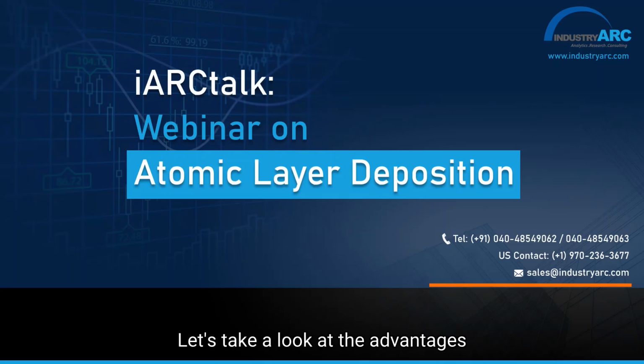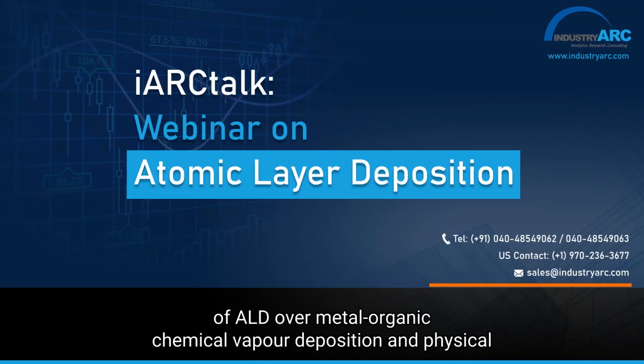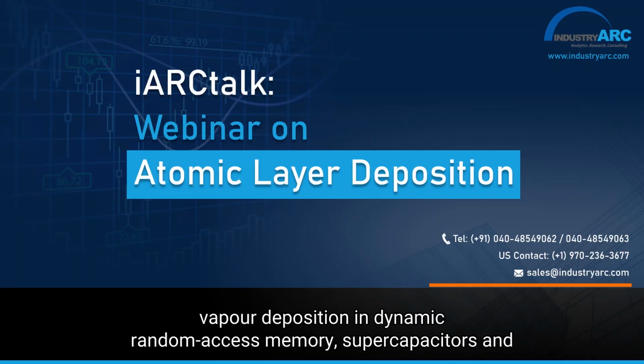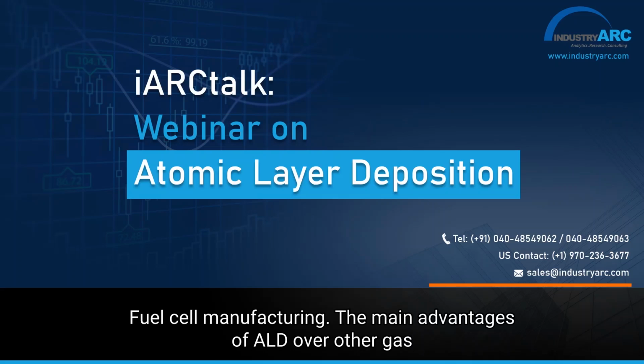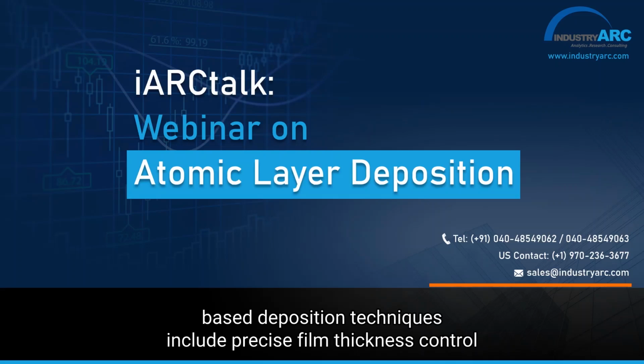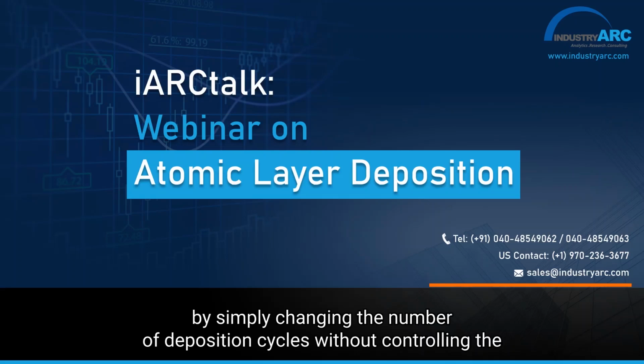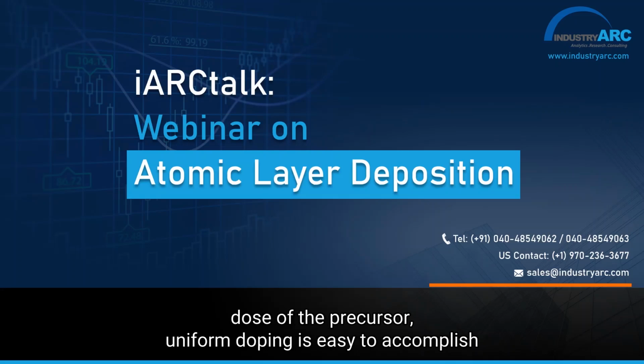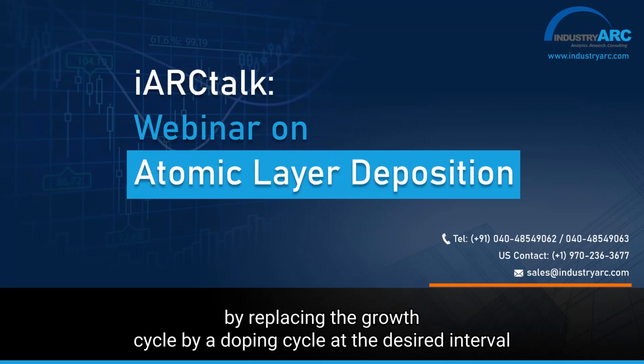participants. Let's take a look at the advantages of atomic layer deposition over metal organic chemical vapor deposition and physical vapor deposition in dynamic random access memory, supercapacitors, and fuel cell manufacturing. The main advantages of atomic layer deposition over other gas phase deposition techniques include precise film thickness control by simply changing the number of deposition cycles without controlling the dose of the precursor. Uniform doping is easy to accomplish by replacing the growth cycle by a doping cycle at the desired interval.